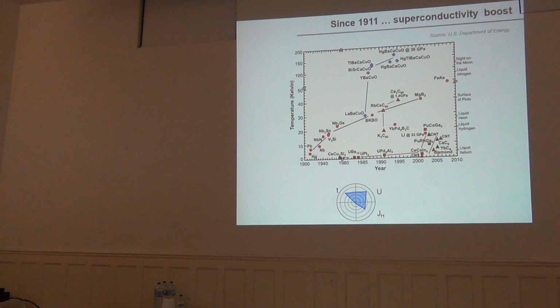Magnesium diboride, which Paul has been working a lot with, came as a surprise because the TC of this system is almost 40 Kelvin, and it was not expected to have a material where superconductivity is phonon mediated at such high temperatures. But these are those that we understand. Now here you see these high TC cuprates with TCs up to 150 Kelvin, and these are materials which are strongly correlated. It's not phonon-mediated superconductivity. There is a lot of discussion about the origin of the superconductivity, but correlation plays an important role here.